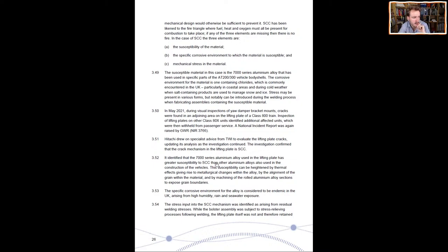The TWI also identified that 7000 series aluminium alloy has a greater susceptibility to stress corrosion cracking than other aluminium alloys. And that can be heightened by the thermal effects, basically the welding process, which gives rise to metallurgical changes within the alloy. That's usually a realignment of crystals, or perhaps the formation of imperfections within the alloy. Alloys are a crystalline matrix, so you get different crystals all interacting. Generally with an alloy, you want it to be as homogeneous as possible. Someone who's a metallurgist, correct me on that, but you want it homogeneous so that the behaviours are as uniform as possible.